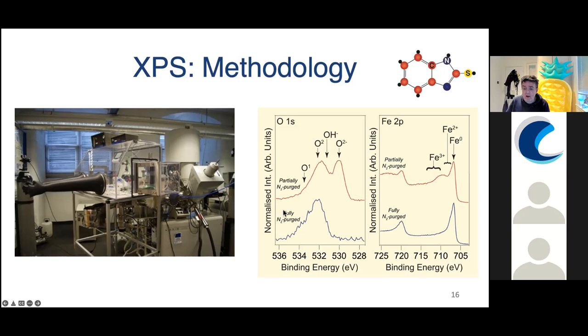taking the sample out from a fully purged glove box and putting it into the spectrometer, or from a partially purged glove box. That means there's some oxygen. And the important point to notice is that if we're not fully purged, we get ionic iron, Fe2+ and Fe3+, whereas we only see metallic iron, Fe0, if it's fully purged. And that's showing that there's post-immersion oxidation.